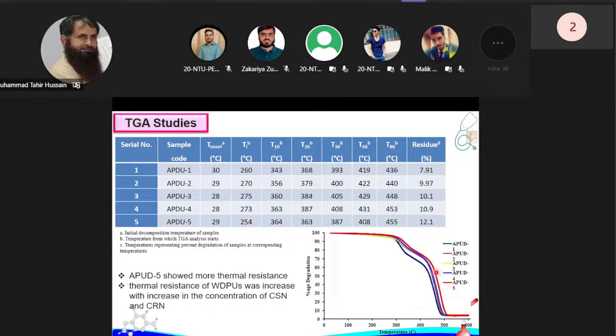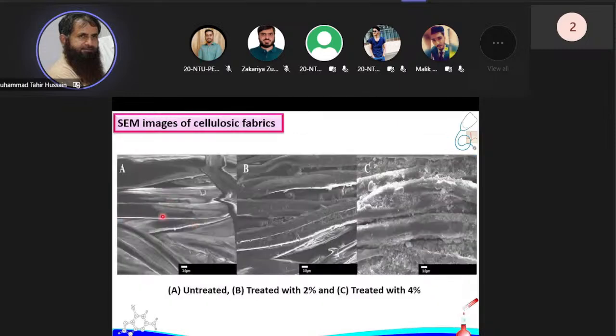We have studied the coating of our finishes using the SEM analysis. This fabric is showing no concentration because it is untreated fabric, and this fabric treated with 2% emulsion finish is showing a small amount of finishes appeared on the yarns of the material. And this material is treated with a 4% finish, and that shows the highest concentration of APUDs over